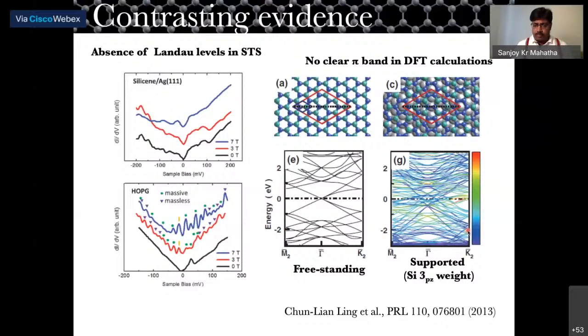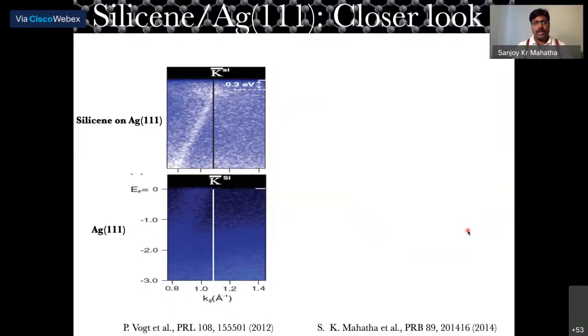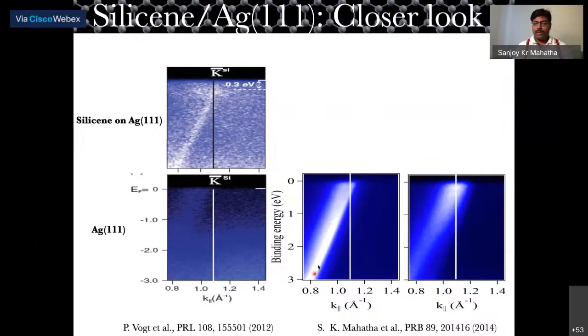And from this point we decided to do the experiment on silver 111. We grew the same film, and we did a similar kind of experiment using the same photon energies and similar conditions. So these are the band structures reported in this PRL. We did the same experiment on silver, and we found this silver band on both sides of the detector, which was not reported in this PRL paper.